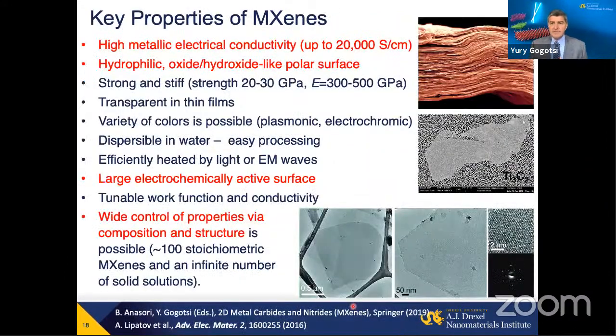So basically, we get a large variety of two-dimensional materials, a couple of atoms in thickness up to, say, 9 atoms, with 6 that we can make distinctly so far. The key properties are high metallic electrical conductivity for the majority of them. This is, for example, a multi-layer film of Ti3C2. And I know Rick Kaner showed a multi-layer film of graphene or graphene oxide, which looked exactly the same actually. So there are similarities.